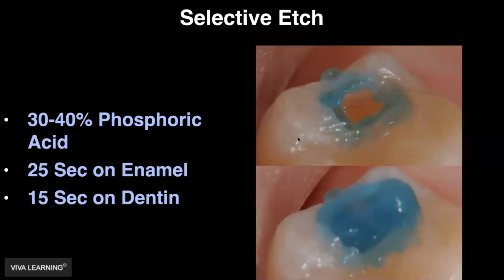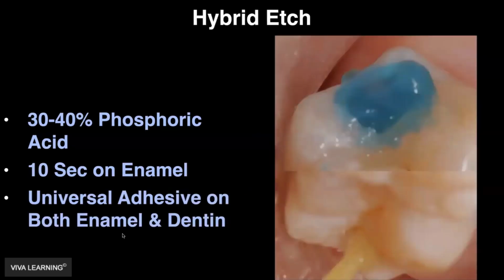So selective etching is still a pure phosphoric acid situation, but we're actually using two different amounts of time, one for enamel and then one for dentin, so that we avoid both under etching enamel and over etching dentin. And then the other technique that's sort of in the middle is hybrid etching.